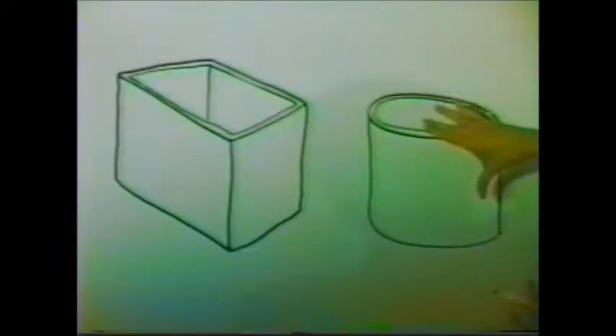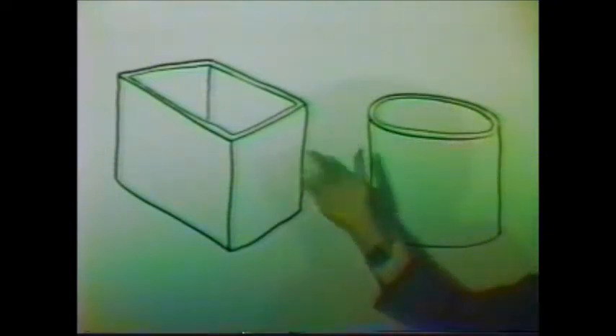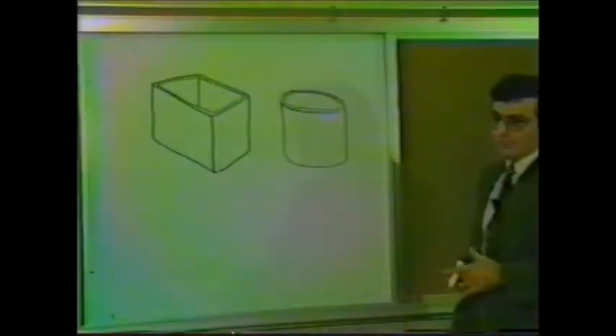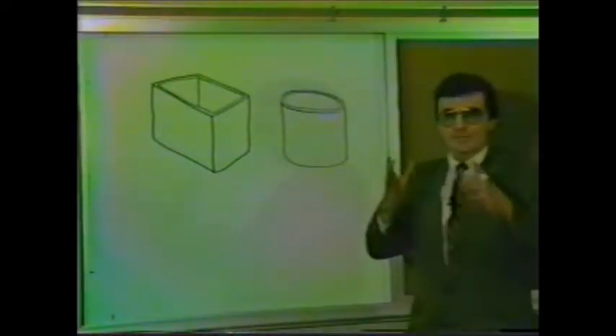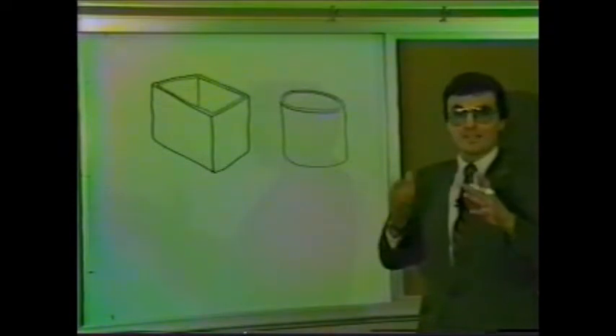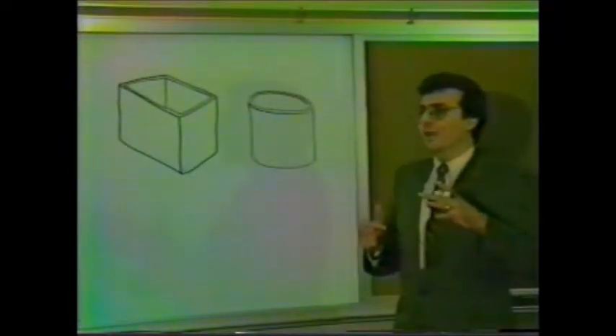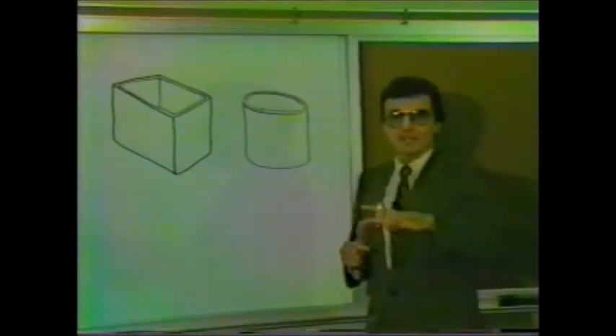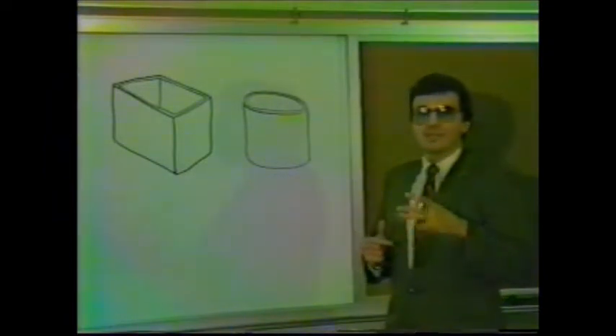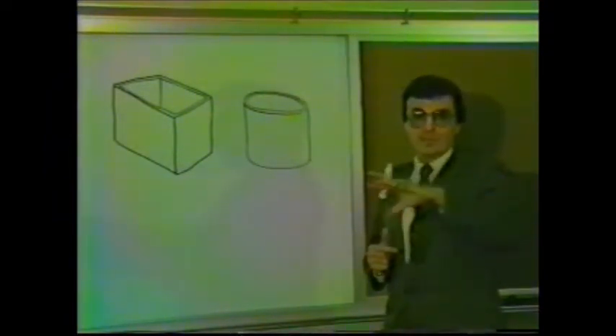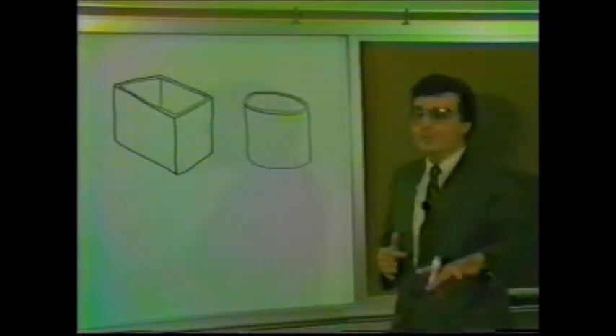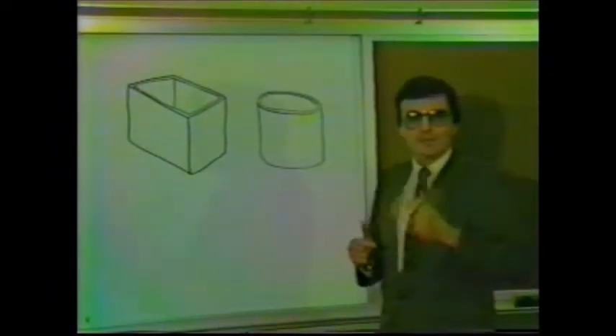By comparison with ingot cast steel, strand cast is much more uniform from the beginning of a heat through to the end of a heat. On an ingot cast steel, which is basically a batch process where the steel solidifies in the actual ingot mold, there are phenomena that happen in the ingot: for example, the top of the ingot is different in properties than the middle of the ingot, which is different from the bottom of the ingot. It's a solidification type of phenomenon.